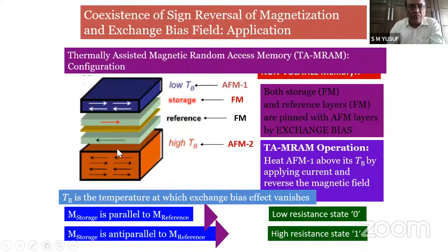memory. You all know that this is the antiferromagnetic layer, which is exchange coupled with this ferromagnetic layer. This is another antiferromagnetic exchange coupling, but this is more rigidly exchange coupled. So this serves as the reference layer, and this is the storage layer, where the storage layer magnetization is antiparallel or parallel, which gives two states. Now this is done by applying a DC magnetic field to reverse it.